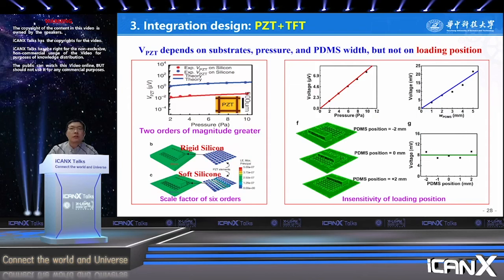It results from the deformation of the PZT array. The FEA, the finite element analysis result, shows there exists a scale factor of 6 orders between the device mounted on the silicon and on the soft substrate. The right figures exhibit the output signal increasing with the applied pressure. More importantly, the effect of loading position, from left to middle and right, is also very critical for practical application. One can observe that the output signal is not sensitive to the loading position. It makes it easier to stick the sensor on the skin.